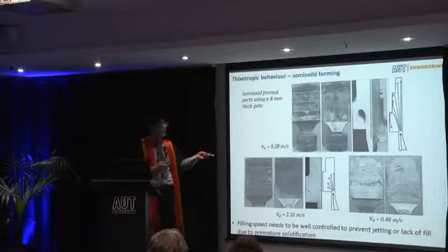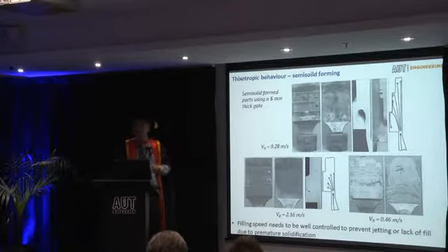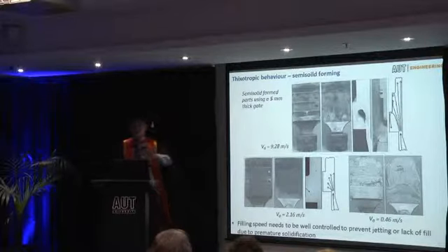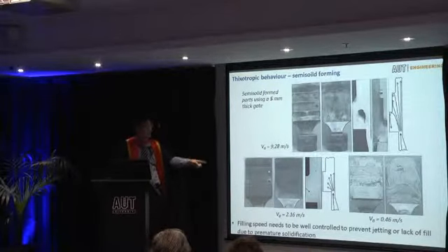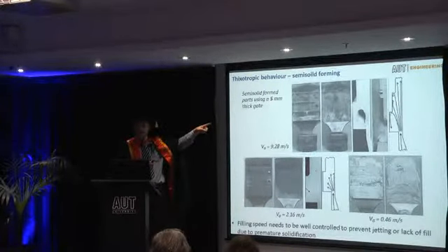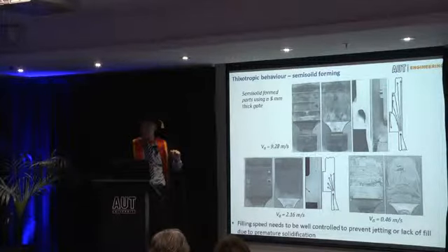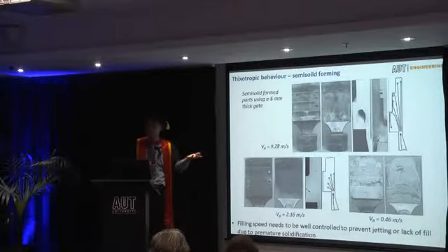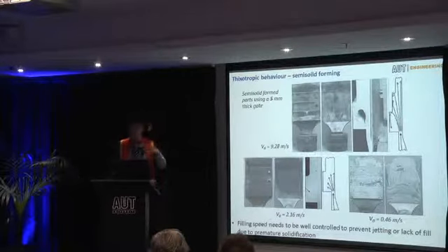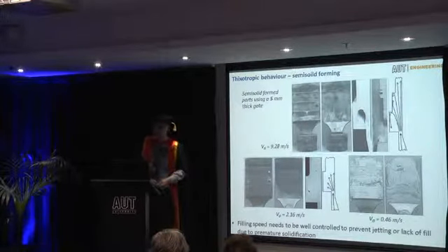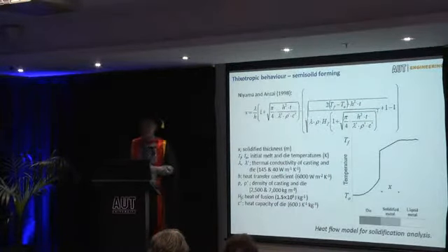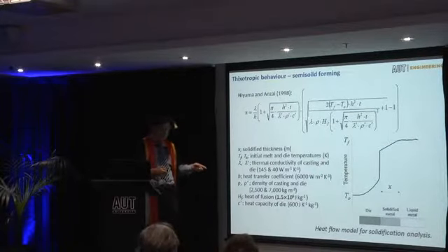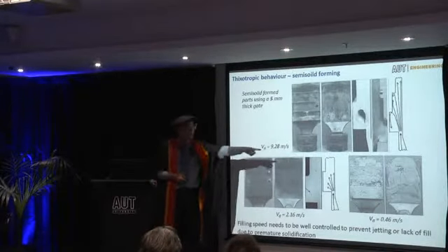I demonstrate by one of the experiments we did when I was in CSIRO: just by varying the velocity, you can see if you have a little bit high velocity, you have jetting. Low velocity, you can't fill the die. Not like liquid. Liquid has a reasonable tolerance in a way. Semi-solid does not.